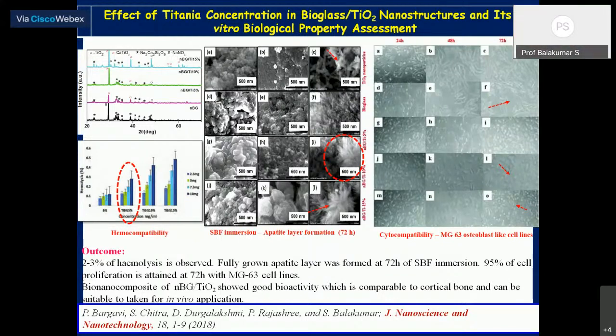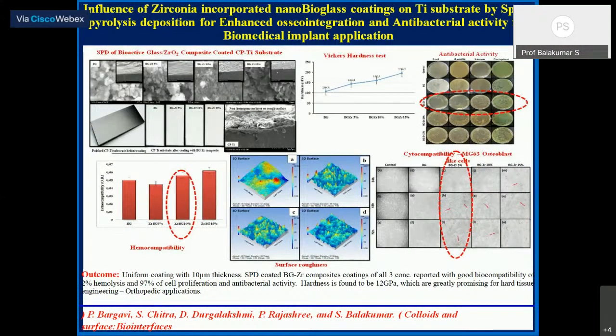We also incorporated different hard metal oxides, because zirconia, alumina and titanium are relatively mechanically strong. We improved the mechanical property of the material by incorporating zirconia oxide. So the hardness improved, and anti-wear was relatively good. The surface roughness is also uniform and can be controlled. That enhances the adhesion of the cells and improves cytocompatibility. So that is also what we have studied. This was recently published in Colloids and Surfaces B: Biointerfaces. This is one of the very good materials.